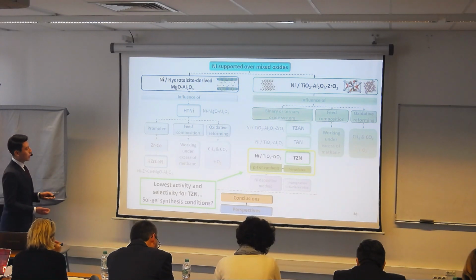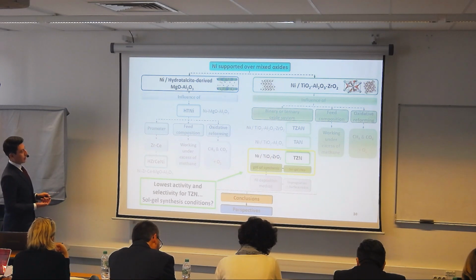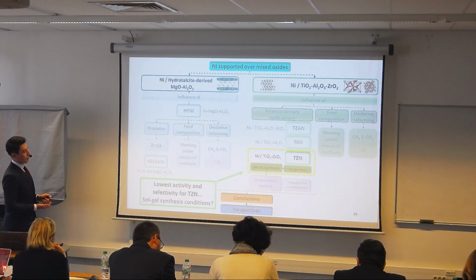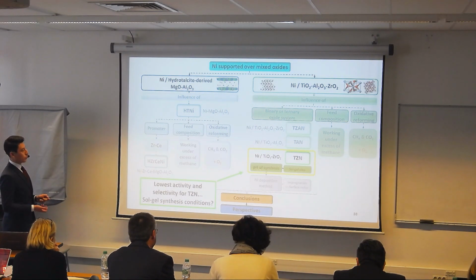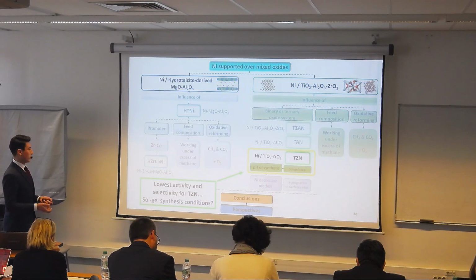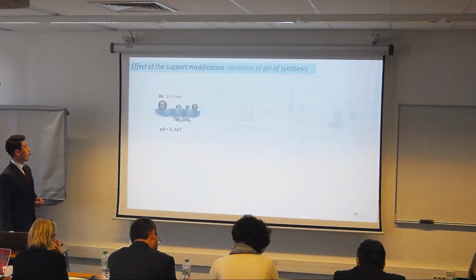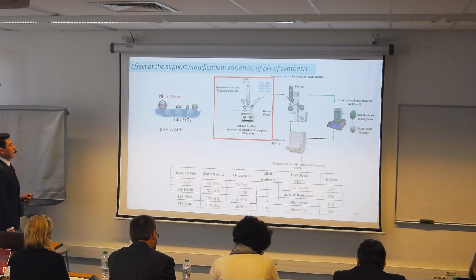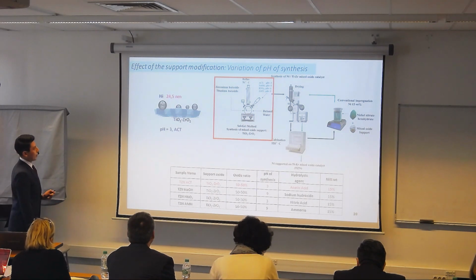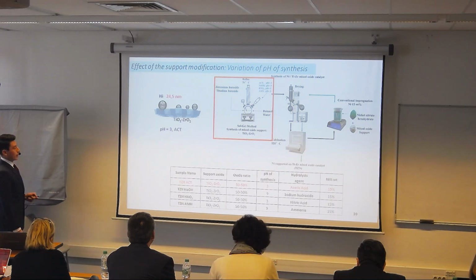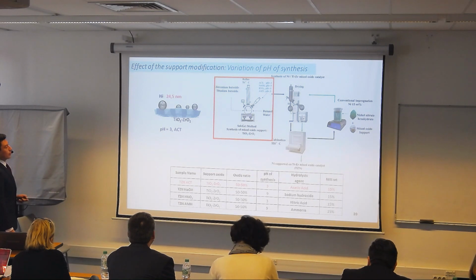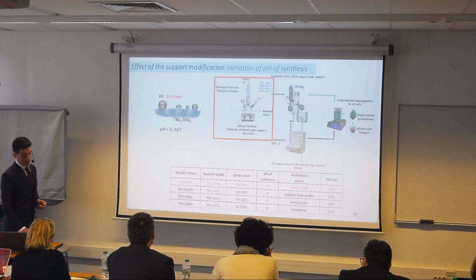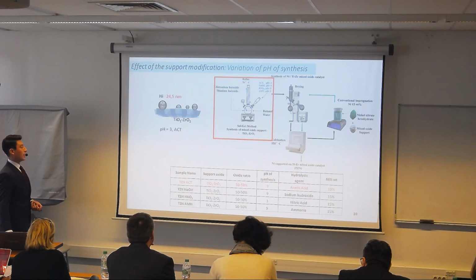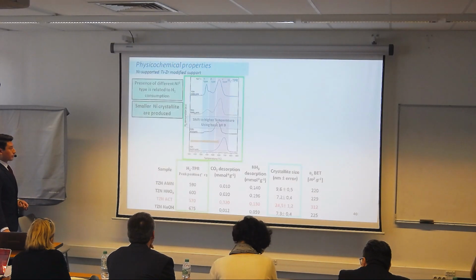So what can we do in order to promote its activity? As I mentioned in the beginning, these catalysts were prepared by the sol-gel method, so we can try to modify the pH during the synthesis. In the beginning we have this catalyst at pH of 3 with a very big crystal size. In this step we are going to modify it to 9 and 3 by different hydrolysis agents, being sodium hydroxide, nitric acid and ammonia.